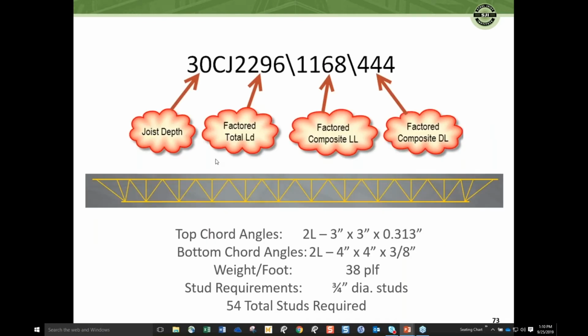Sam talked a little bit about the load designation. So in this particular case, we've picked a 30-inch CJ 2296, 1168, 444, and that particular joist has top chords 3x3 by 313, nice wide chords for welding of the studs, bottom chord angles of 4x4 by 3/8, weighs 38 pounds a lineal foot, 3/4 inch diameter studs, which is the most common diameter stud you're going to see on composite joists. And we've got 54 of these, which is essentially a stud every foot. Just kind of rule of thumb, you're typically going to be somewhere near a shear stud every foot of the joist. It is quite common.